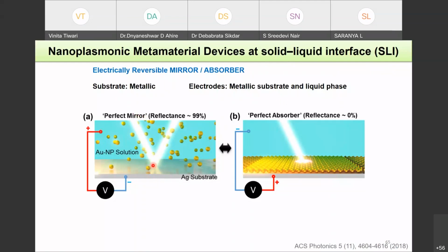You can shine light, and the light will hit the bare silver surface, and you will get complete reflection, like 99% reflectivity that you typically get from a silver mirror. But as soon as you alter the electrode potential, that is, you make your silver electrode a positive electrode, all these nanoparticles will come and settle down, and they will form a 2D array. And this 2D array will be able to absorb your incident radiation, and you will get almost zero reflection. And this system is basically a reversible system, as you can understand. If you alter the potential, you can quickly change the system from a mirror to an absorber.